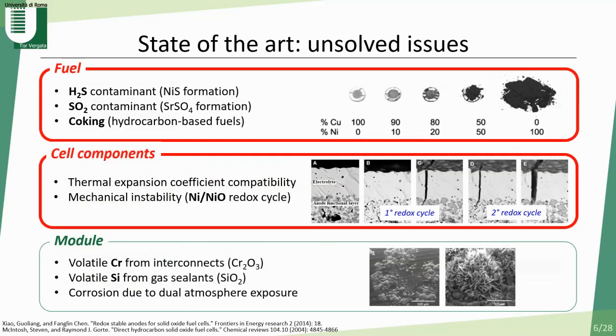Especially the fuel flexibility and mechanical stability. Specifically, the presence of nickel in the anodic cermet produces mechanical instability due to the continuous reoxidation from nickel to nickel oxide during the redox cycles, which leads to anode detachment. In the presence of fuels different from hydrogen, such as methane mixtures or hydrocarbons, nickel promotes carbon deposition and coking formation. Moreover, it is easily contaminated by sulfur components.